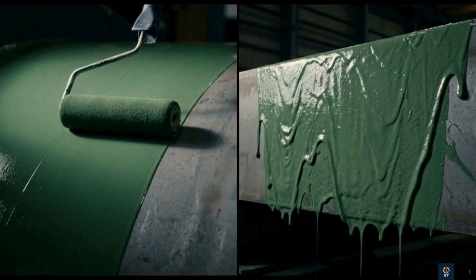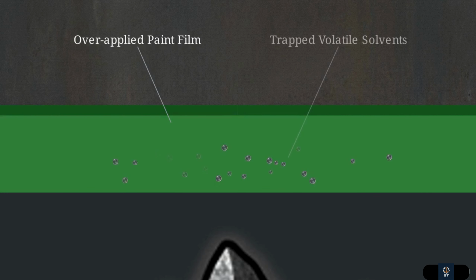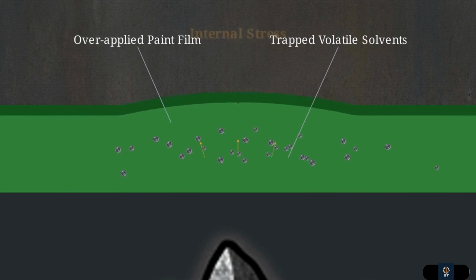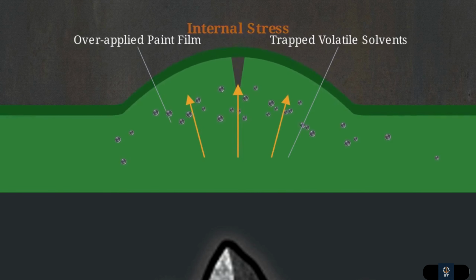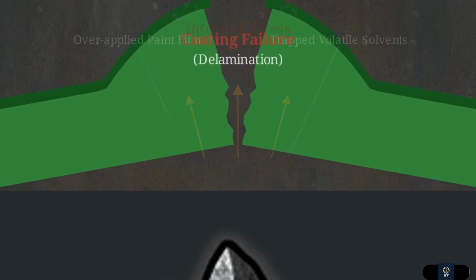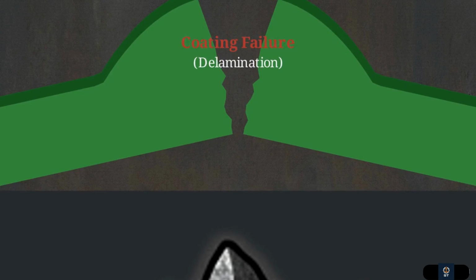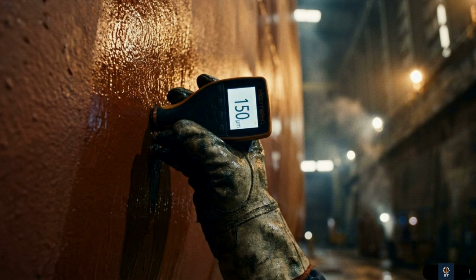You might assume applying more paint would offer better protection, but over-application is actually catastrophic. This cross-section shows what happens when paint goes on too thick. Volatile solvents get trapped inside the film. As they try to escape, they create massive internal stress, causing the expensive coating to crack, blister, and peel away. In marine coatings, applying more paint doesn't increase your defense. Survival requires absolute chemical precision, measured meticulously in exact micrometers of dry film thickness.